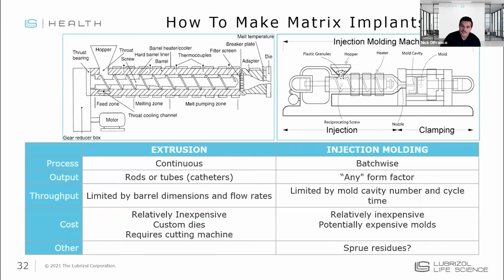Once you have that drug-loaded polymer, you can then put it back through a second extrusion process, at the end of which you have a die that forms your device into whatever form factor you're trying to achieve. This could be a rod, it could be a tube, a film. You have a lot of customization with the shape of your final device. You can also put your material into a heated mold, using an injection molding process.